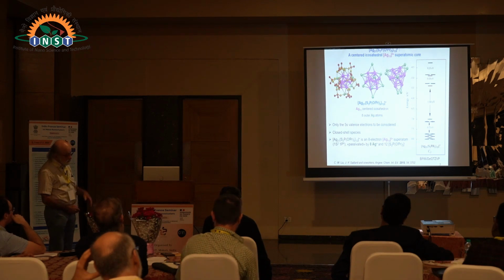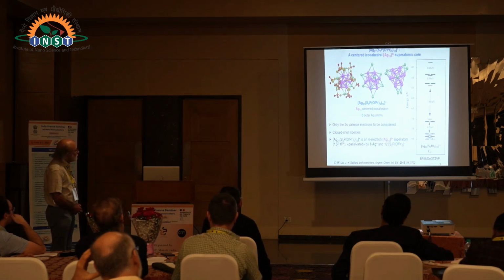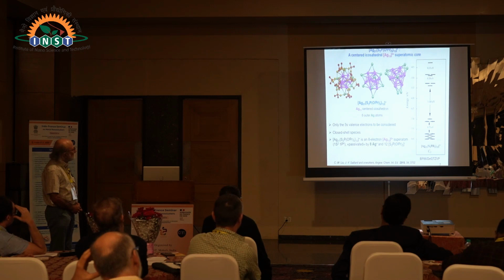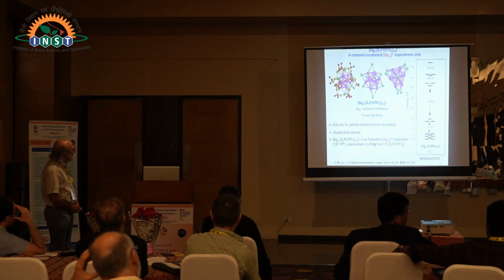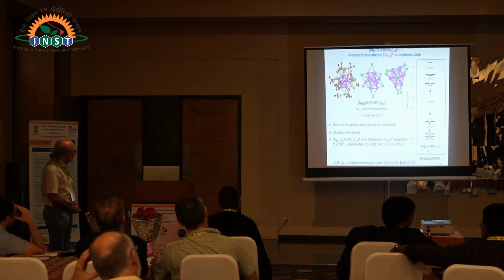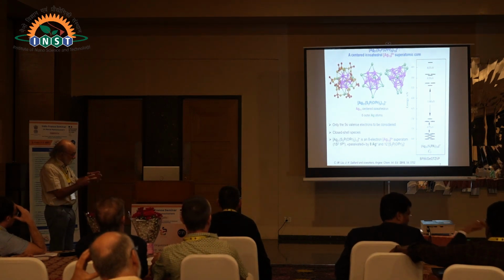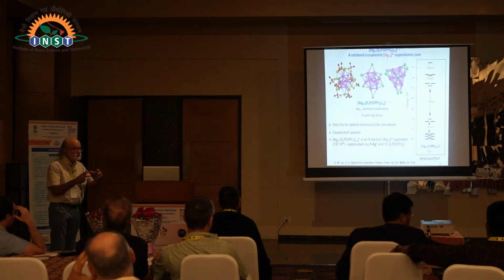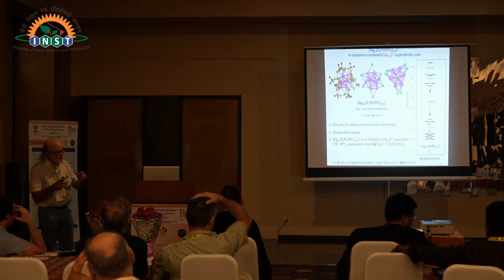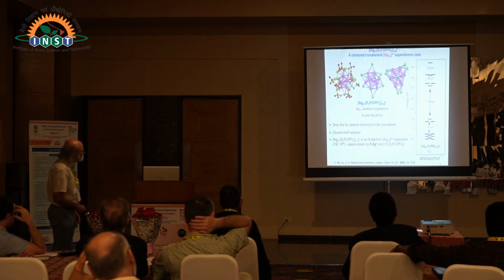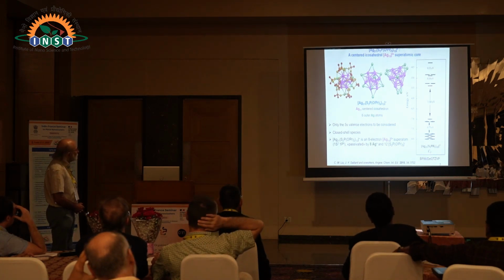Looking at the electronic structure and the molecular structure allows us to divide the 21 silver atoms into 2 categories, the pink ones and the green ones. The pink ones are making a silver 13 centered icosahedron. A centered icosahedron is something very compact, almost as compact as FCC or HCP. And the green atoms.